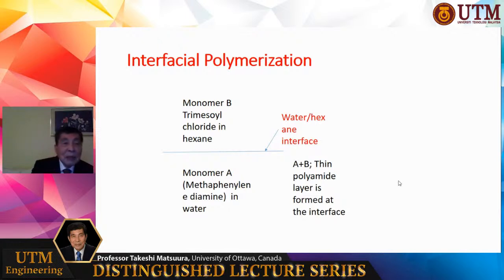The second way of making the membrane is based on so-called interfacial polymerization. This polymerization method means one monomer A, like metaphenylene diamine, is dissolved in water. This is a water solution. And the other one, monomer B, like trimesoyl chloride, is dissolved in hexane. And they are put together. They are in contact with each other, but they are not miscible. They can't be dissolved in each other, so they are not miscible.